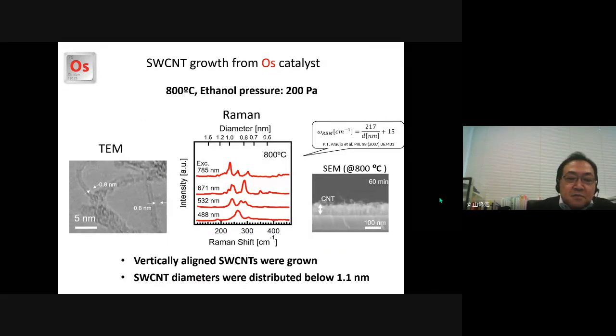So we succeeded in vertically aligned SWCNT growth. Although the length was short, about 50 nanometers, the diameters were below 1.1 nanometer, which were similar to those from platinum and iridium catalysts. So we demonstrate that platinum, iridium, and osmium, so platinum group elements in period 6, are suitable to obtain small diameter single-wall carbon nanotubes. Next slide, please.